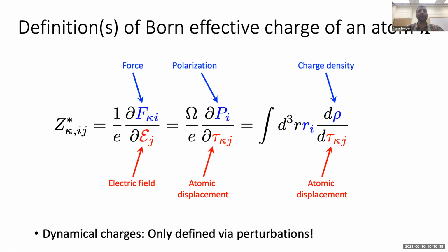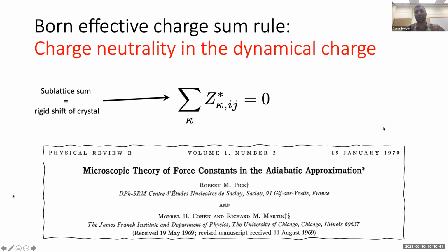And so one of the interesting things about the Born effective charge is that even though it's a dynamical charge, it has at least one element that is related to a partitioning of a static charge, in that there's a charge neutrality condition for the Born effective charges. What I mean by that is if we take an element of the Born effective charge tensor, we sum it over atomic sublattices, then that quantity should vanish in a crystal with translational symmetry. And this was shown rigorously in this work by Pick, Cohen, and Martin, and is a result of translational symmetry and overall charge neutrality of the crystal.